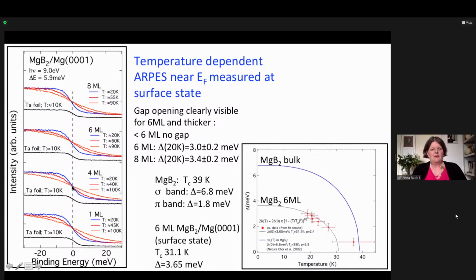So the first layer is just a normal metal at low temperatures. But when you go to 4 layers, there is no change, still a normal metal. But when you go to 6 layers, you see now the lines don't cross at the Fermi level anymore. And when you go to 8 layers, it goes even further away. So we have a gap opening here. Below 6 layers, we don't have a gap, and above 6 layers, we do.